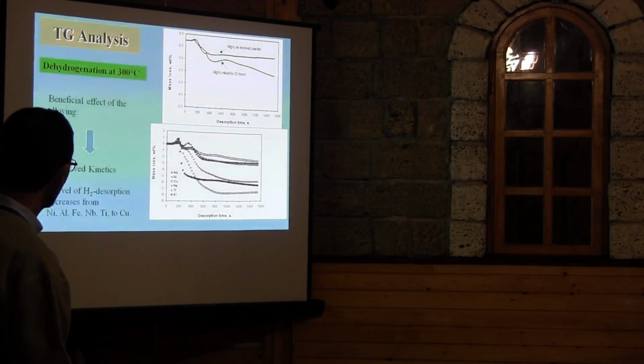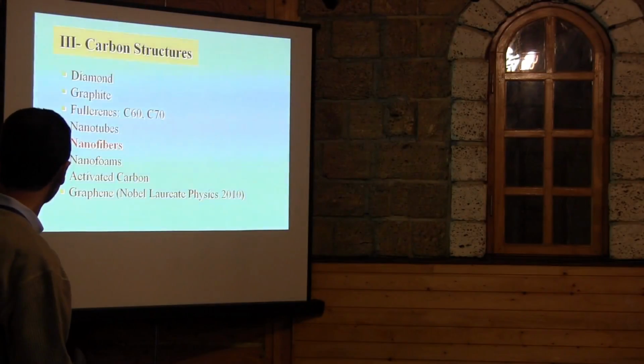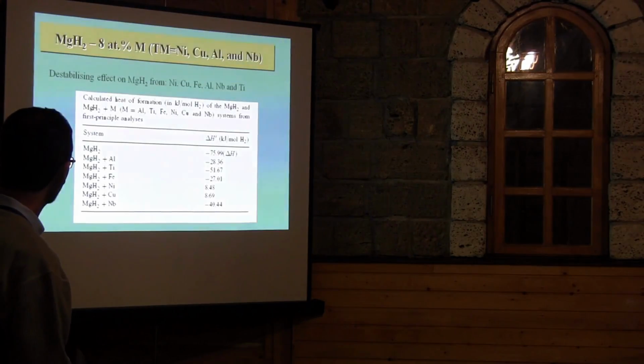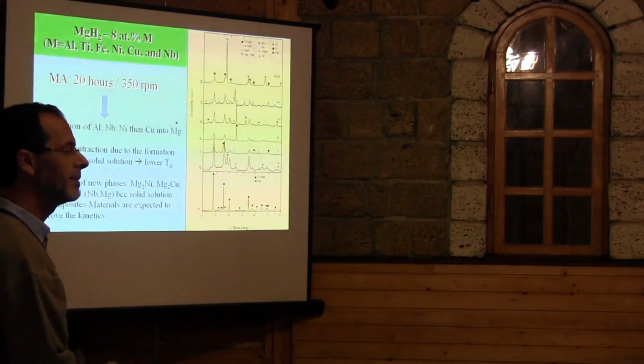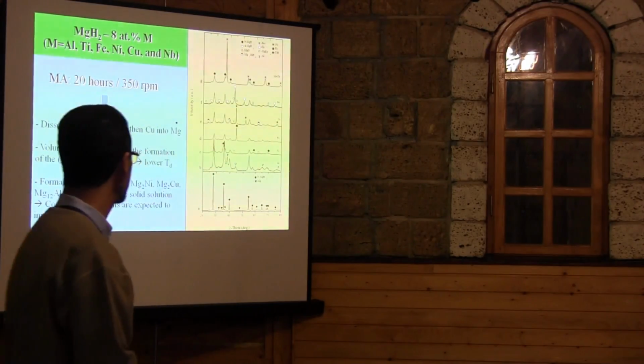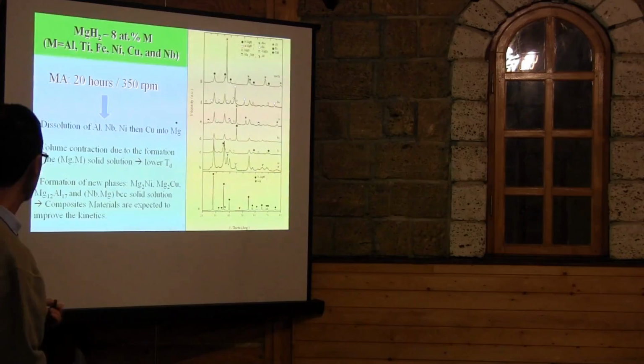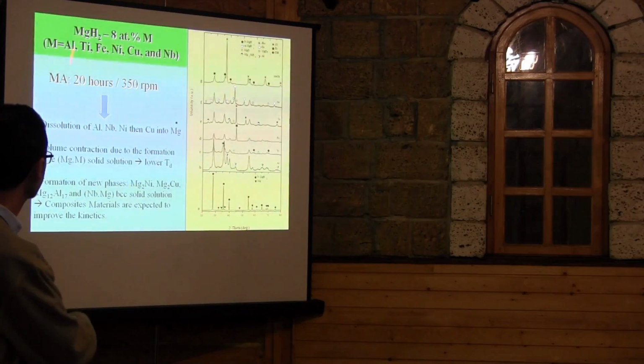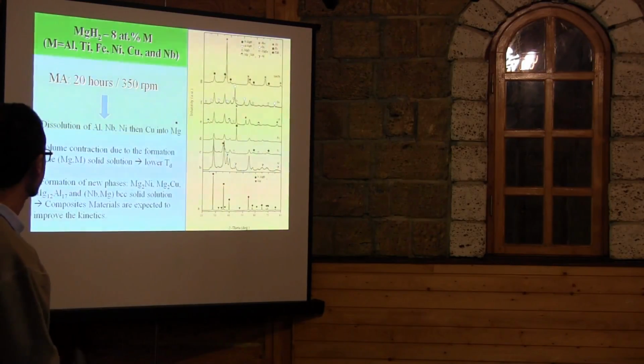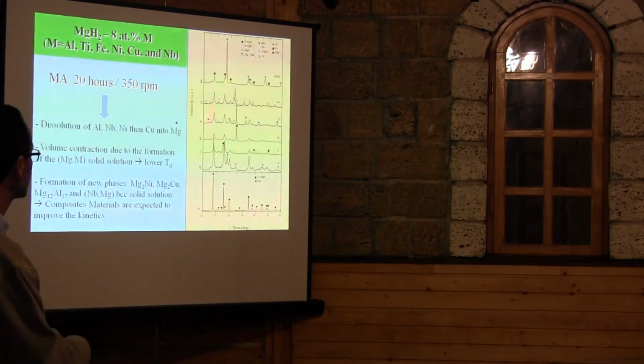So I come back to the experiment. We prepared this sample by mechanical milling. We mixed magnesium hydride with 8% of metal, and we did mechanical milling, and this is what we obtained.